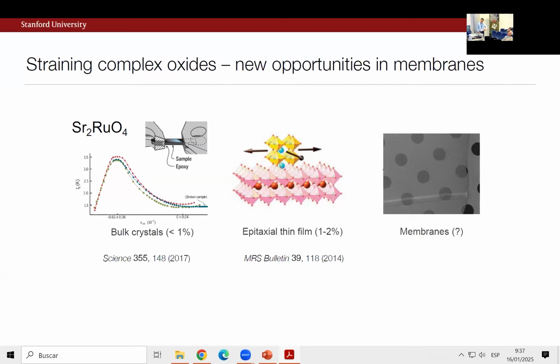So already in our community, strain has been an enormously impactful research tool. These are just a few examples, but for example, in single crystal quantum materials, there is this famous strontium-ruthenate superconductor. By applying uniaxial strain, people found that the superconducting transition temperature can be shifted quite widely, right? And what was interesting and motivating them was thinking about a different way to probe, for example, the order parameter symmetry in the system.